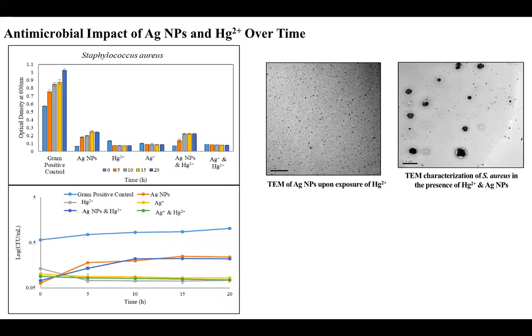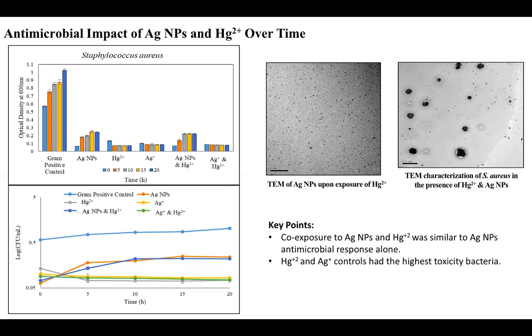All right, and we were also able to do the same when we look at silver nanoparticles and mercury over time. Now, unlike cadmium, mercury is extremely toxic to our bacterial strains and is easily uptaken, transformed and broken down. It's even more toxic than silver nanoparticles and very similar to silver ions alone. But what's interesting again, when we see silver nanoparticles and mercury in co-exposure, it still follows the trend of silver nanoparticles alone. So it indicates that these nanoparticles could be blocking the availability of these metals close to the bacterial cell or the uptake by the bacteria.